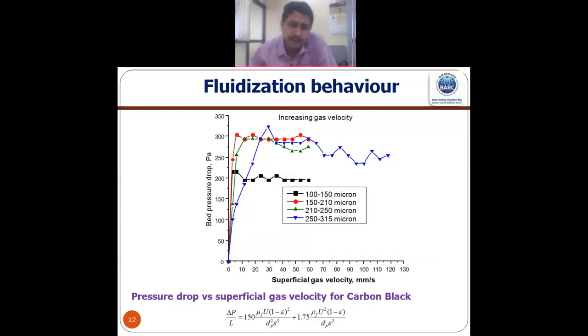So in order to ensure the fluidization is happening, how do we know that proper fluidization happens? Here we measure the bed pressure drop against the superficial gas velocity, and we get a typical plot like this. Initially, when the gas velocity increases, the bed expands and the bed pressure drop increases. At the point when fluidization starts, the pressure drop suddenly decreases slightly, and then it is constant. By monitoring the pressure drop, we can understand that the bed is properly fluidizing. There are also theoretical calculations to find the minimum fluidization velocity, given by the Ergun equation. That is the theoretical calculation, and experimentally, we can find it out by bed pressure drop versus superficial gas velocity.